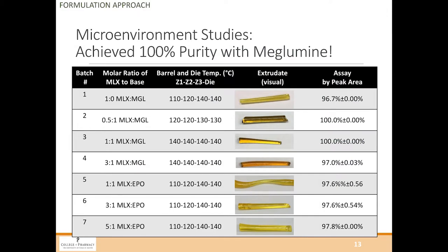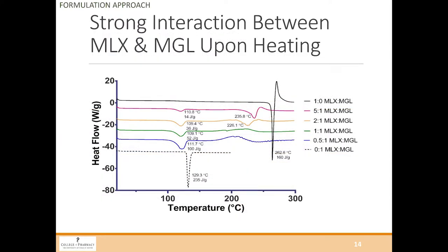I'll come back to some of that. So, basically, briefly, when we have 1-to-1 molar ratio, we actually are able to get rid of all the degradation. So, what's happening here, we actually form a salt, in situ salt, during the extrusion process. Okay? And look how stable they are, especially at 1-to-1 molar ratio. When we prepare a physical mixture between meloxicam and meglumine, this one here is meloxicam on the top. After melting, it actually degrades, right? This is the melting point of meglumine, 129 degrees.